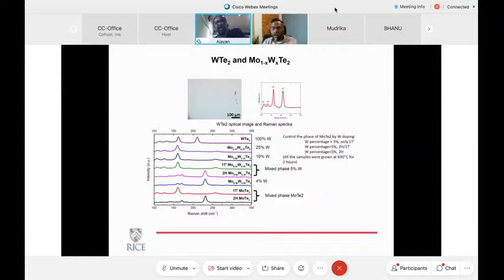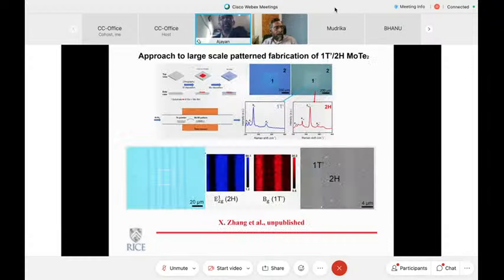And one thing we realized is that if I take molybdenum telluride and start to dope it with tungsten, you start to see only the metallic phase. So the tungsten-doped molybdenum telluride essentially falls into the 1T prime phase of the tungsten telluride system. So that kind of brought us to this idea that if you can controllably dope only certain regions of the MoTe2 that is being grown, those regions will become metallic.